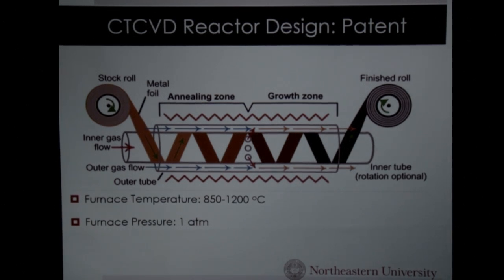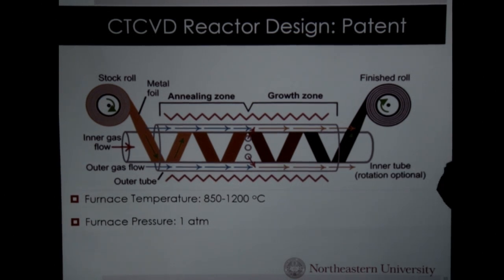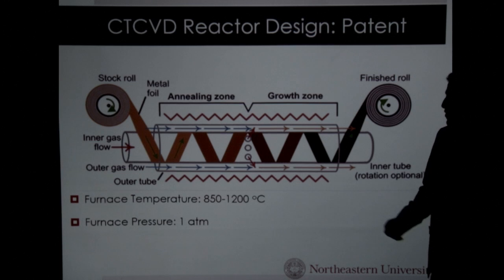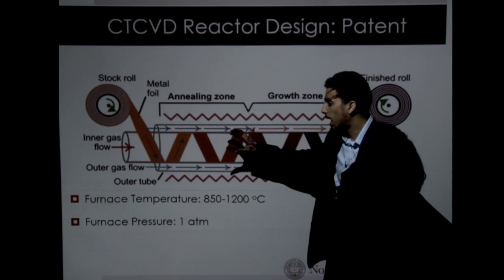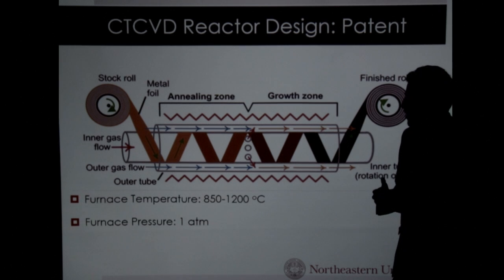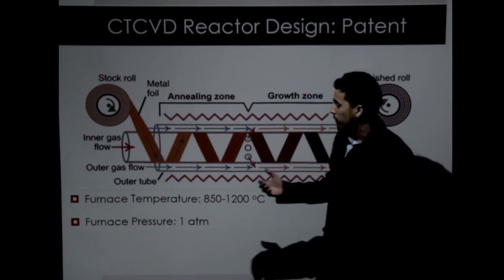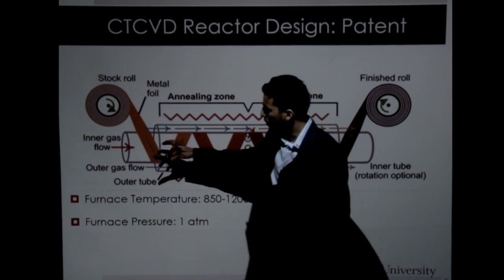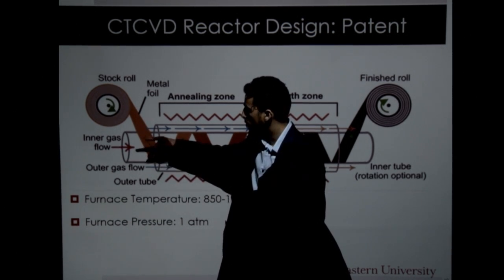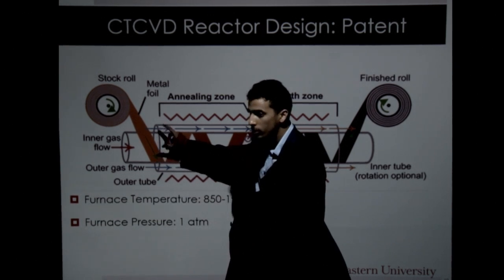And here's the design of our CVD reactor. So the uniqueness and significance of this design centers around the concentric tube. By adding an inner tube to the existing tube, they were able to reduce the amount of gas used by 90%. So basically, you can either enter the whole volume of the gas to your system, or reduce it by adding the other tube. So you have a smaller volume here, which is the confined volume between the inner and the outer tube.